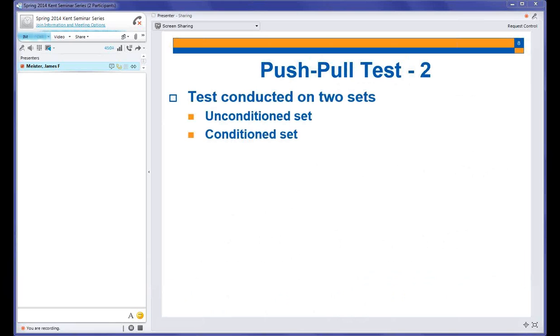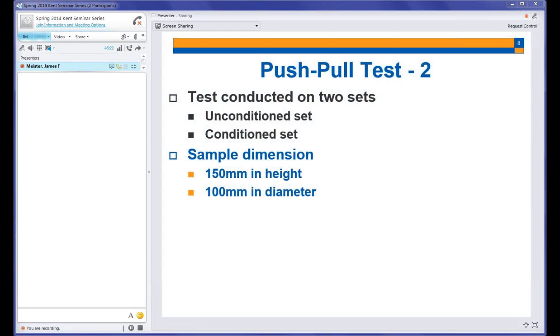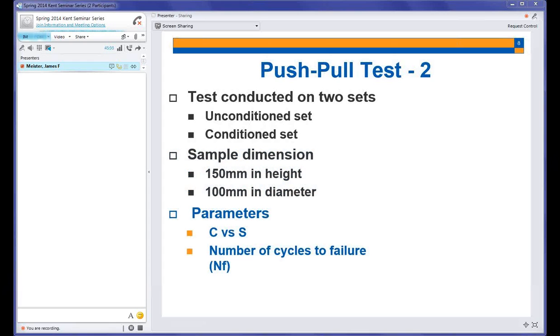Also, it was tested on 2 sets, unconditioned and conditioned. Here, for unconditioned, we don't put it in water whatsoever; we prepare the sample and test it immediately. The conditioned set, again, could follow a procedure, Illinois modified, 2, 3, but as mentioned in the objective, it was only 5 freezing thawing cycles in this study. Sample dimensions are similar to the samples used to measure the complex modulus of asphalt concrete: 150 millimeter in height, 100 millimeter in diameter, and we will see why it is similar to the complex modulus samples. The parameters are the pseudo stiffness, which is C, versus the damage parameter S.